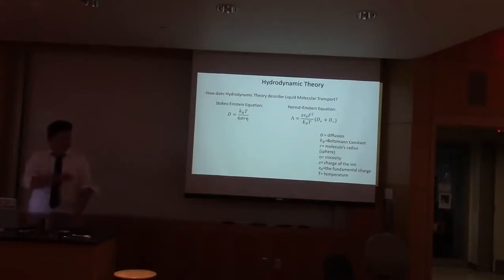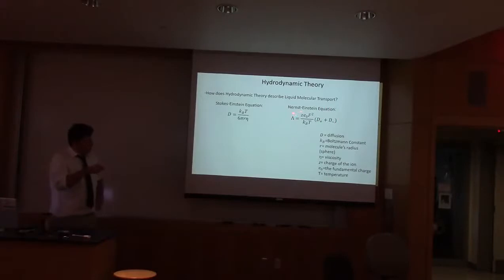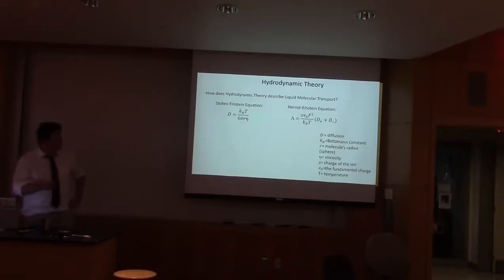We can relate conductivity, or in this case molar conductivity, using hydrodynamic theory by relating the diffusion of the cation and the anion times the charge of the ion, the fundamental charge of an electron times Faraday's constant squared, divided by the Boltzmann factor times temperature. This means that fundamentally the conductivity is related to the diffusion, which in turn is related to the viscosity. See how we're taking macroscopic properties and trying to continue to explain other macroscopic properties.